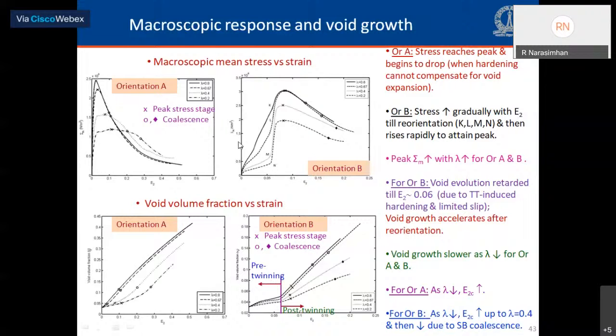In the case of orientation B, if you look at the right side plot, you see a different picture here. The mean stress grows very slowly during the pre-twinning stage, that is up to a strain of about 6%. And then there's a very steep increase in the mean stress as the lattice reorients and as hard systems get triggered, like pyramidal C plus A, then it reaches a peak value and then begins to drop.